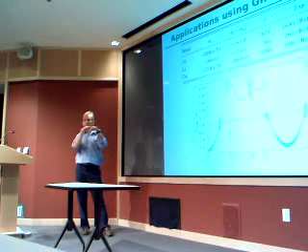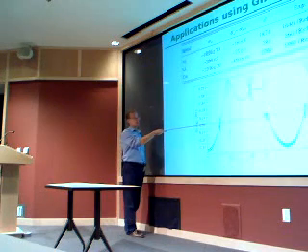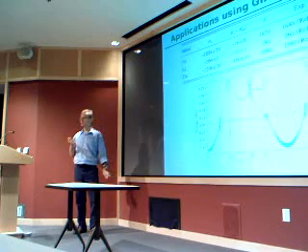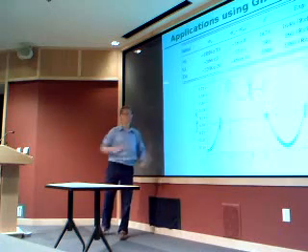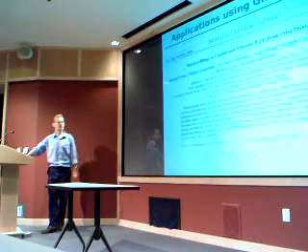The Knight shift is a little bit like the chemical shift, but because you have a metal, you put in the magnetic field, so part of the electrons are shifted or lifted from below the Fermi level with different spin, and some of them become occupied. So it's kind of a response, and of course it's very strong at the Fermi level, because you need only a small magnetic field or small change to get a large change in the electronic structure close to the Fermi level. We also have quite a contribution. So these kinds of things one can calculate in the whole. And then one could quantify this with the Knight shift, this pure number, but I didn't take any examples here.